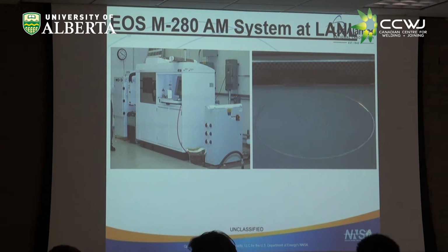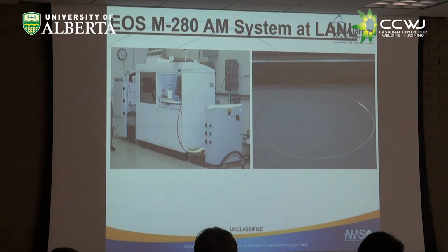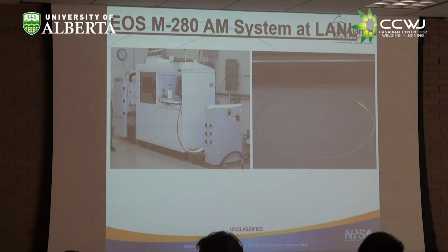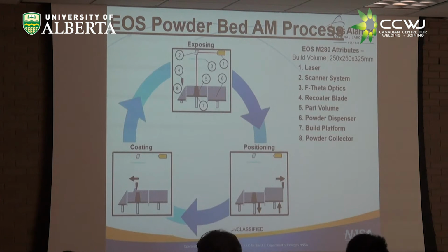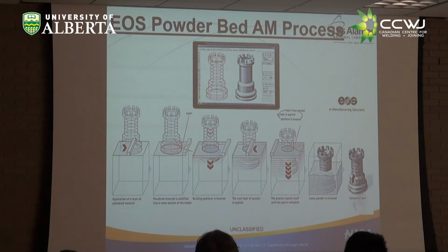Directed energy is a lot like laser welding, and you shoot powder into the melt pool. I'll show you in the next slide or the slide after what's going on. The beam moves very quickly. The beam is moved in this case over a thin layer of powder. It's difficult to see here, but you can see the beam moving here. It's directed by galvanometer mirror, so it moves very quickly. The laser power is not very high. The layer of powder here is on the order of 40 to 50 microns in depth, so it's not that deep.